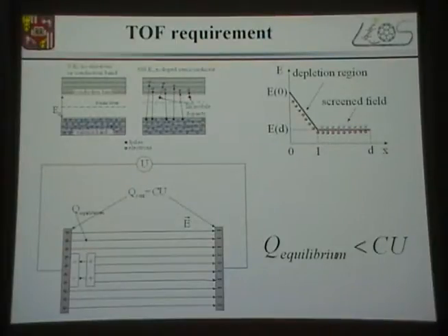Historically, though, time of flight has been the method used the most to study the charge carrier transport in all these inorganic and organic materials. However, the reason we usually cannot apply time of flight in our organic structures is that the organic materials contain a significant amount of impurities, therefore a significant amount of dopants. These impurities in the film result in free charge carriers. As you see here, this will be at zero temperature, and here you see the impurities result in, this is also the equilibrium generated carriers over the band gap, but it should not be many because the band gaps are large in organic semiconductors. But the impurities generate free charge carriers, and if they are present in the film, they participate in electric field screening, therefore the classical time of flight is not applicable.